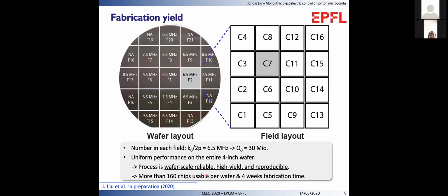We also study the yield of our fabrication. The loss of each sample at a different location on a 4-inch wafer is measured. As you can see here, in most of the locations, 6.5 MHz line width is maintained. This study proves that our fabrication process is wafer scale, reliable, high yield, and reproducible. We can deliver more than 160 working chips on a 4-inch wafer, which requires only 4 weeks of fabrication time.